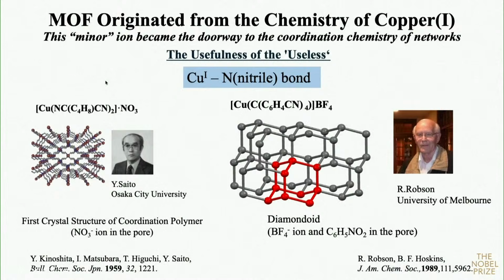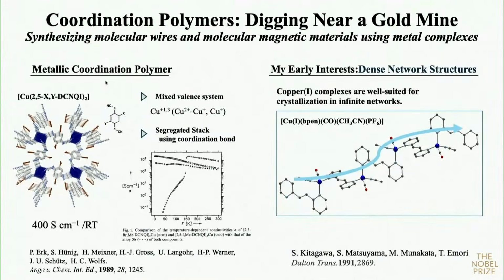Long time ago, Saito synthesized a copper-1 dinitrile ligand system. That is the network structure. This is a fully interpenetrated system. After that, Professor Robson synthesized a diamond-like structure. This has no interpenetration, and accommodates ions and organic molecules. So he also showed the network formation principle. Simultaneously, Hünig synthesized this kind of interesting material using the DCNQI ligand. These DCNQI ligands have a column to show high conductivity. This is metallic conductivity.